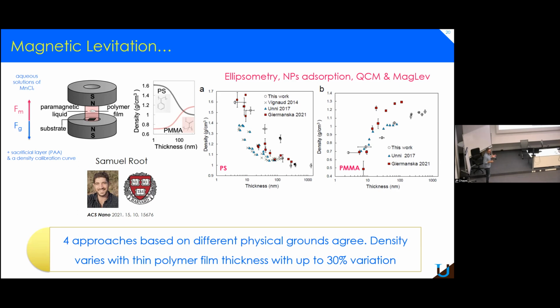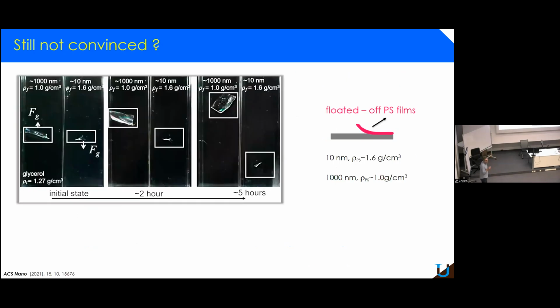So we are quite happy because 4 approaches were basically leading to the same conclusion, that density might vary in polymer films, for polystyrene increasing a lot and PMMA increasing a lot. So if you are not convinced, this is a very clever experiment that someone did.